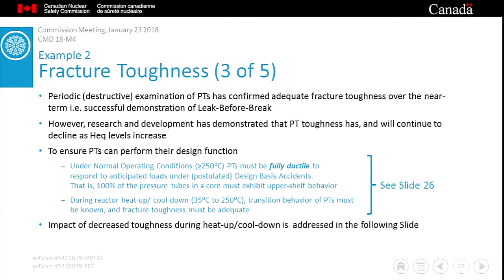However, when pressure tubes are operated below 250 degrees C, for example during the heat up and cool down of the reactor, the situation is more challenging. Based on a detailed understanding of how toughness changes with both hydrogen content and temperature, operators must carefully control heat transport system pressure to ensure that at each step, pressure tubes will be sufficiently tough.